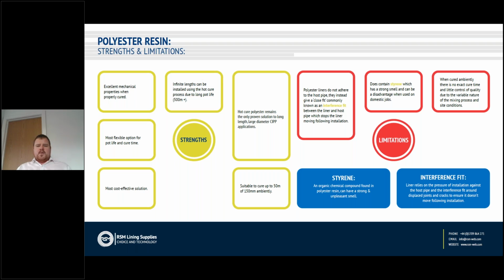The product does, however, have its limitations. Obviously, the product does contain styrene, which is a volatile organic compound. We must make sure that when curing the liner, we do so correctly to the manufacturer's recommendation to get the minimum residual styrene within that liner for the best mechanical properties, but also to make sure we have the minimal impact on the environment.